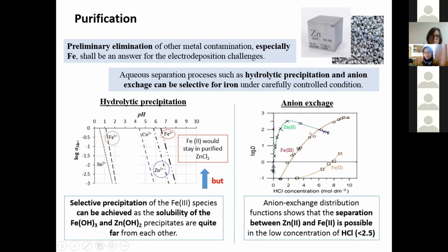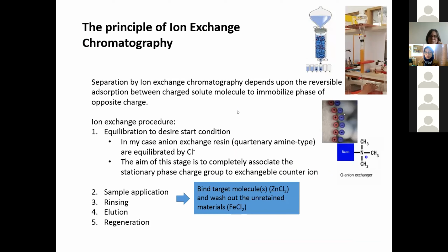But in anion exchange, we can get both in the liquid stage, so we can electrodeposit either zinc or iron here. Here we can see the anion exchange distribution functions for the iron and zinc. The separation lane here can be drawn here. If we have trivalent iron in the solution, it's better to do it below 1 pH. But if we have divalent iron, we can widen this range to 2.5, so we can have a wider working range. And it can be done by reducing the trivalent iron to divalent iron. And this is the principle of ion exchange chromatography, by the way.